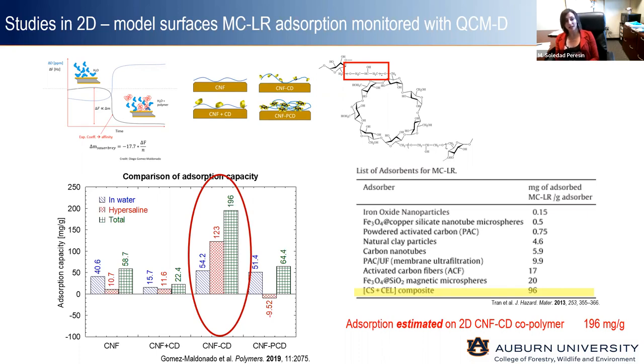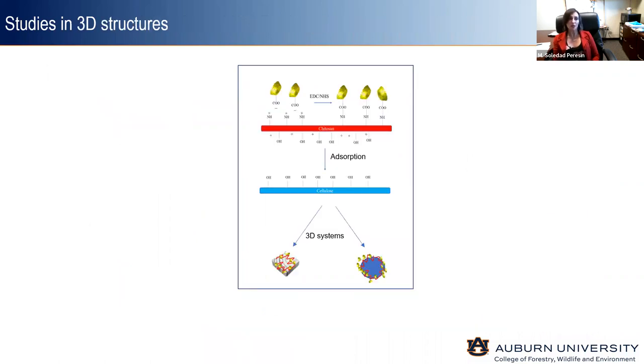Now, this adsorption estimated, and I bolded and italicized estimated, onto this two-dimensional nanofibrillated cellulose cyclodextrin copolymer was much higher than those reported in the literature. But this, again, needs to be taken with a grain of salt because it's a model system. However, we identify this as a very promising system to move forward. So what we did next was to assemble this two-dimensional system into 3D. We used the same modification with the cyclodextrin, but instead of grafting directly to the cellulose, we used chitosan as a substrate and used the inherent adsorption capability of the chitosan onto nanocellulose surfaces to create these systems.